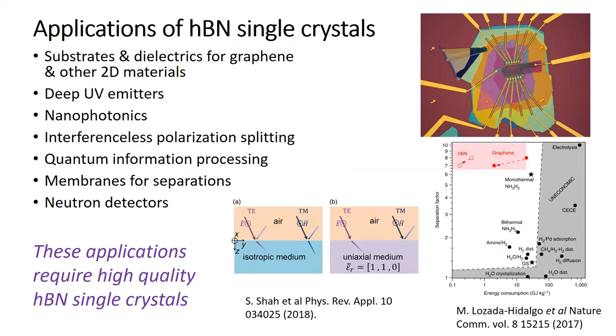Membranes: people are using boron nitride for separations. It turns out that hydrogen and deuterium can diffuse through these thin layers with high separation factors, so it's good for separating hydrogen isotopes at relatively low energy in comparison to something like distillation, which takes a lot of energy to separate. Other applications, certainly substrates and dielectrics for graphene and other devices as shown here.